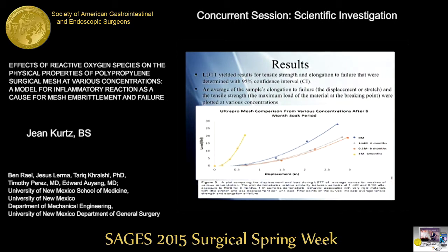But these are actually still stretching a fair amount, but you'll notice that the tension, the load of failure, is still significantly lower than the fresh meshes. This was around 17 and a half pound-force for the physiological concentration meshes. And the reason that they're on either side of that blue curve in displacement is because we think they're taking on a more quasi-crystalline property, as was hypothesized. So yellow is a very rigid material, and then we have a quasi-crystalline material that's not as strong.